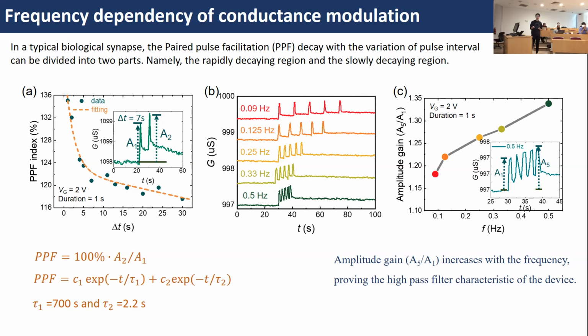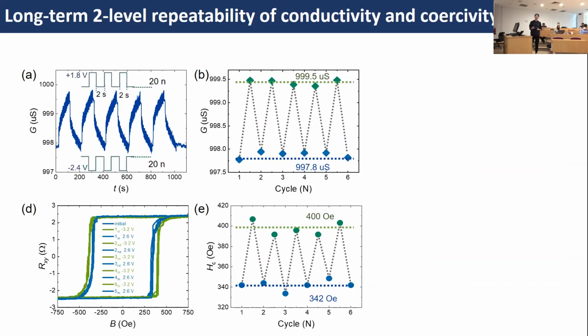For the tau1, according to the calculation, it's around 700 seconds, and for the tau2, it's around 2.2 seconds, which means that it can be divided into two parts. The first part is the short-term memory, and the second part is the long-term memory. And it also responds to the gate voltage of different frequencies. It means that with a higher frequency, we will obtain a higher amplitude gain, which means that it can work as a frequency filter. Okay, and this device also shows good repeatability, with both the conductance and the coercivity switching between the two states, the high level and the low level.